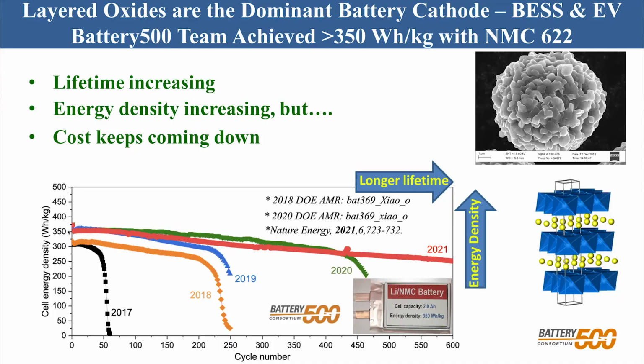So we're still busy working on that, and I should emphasize the materials we use are what we call these meatballs. They're about 10 microns across. The primary particles are a few hundred nanometers in size. And those cause some issues, and I'll get back to that. But I want to emphasize all the data I show you on these slides is real data.